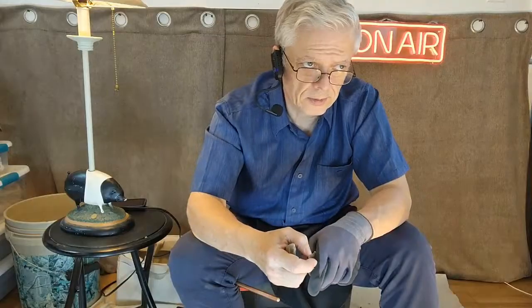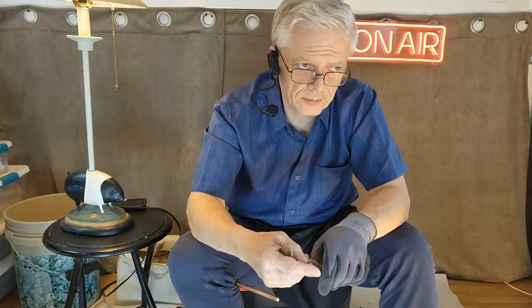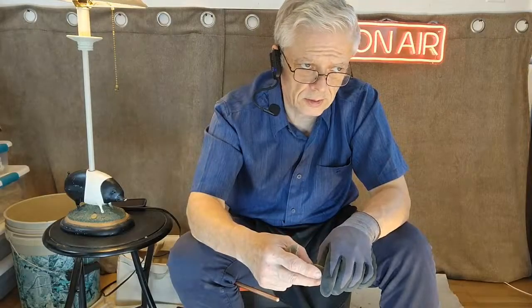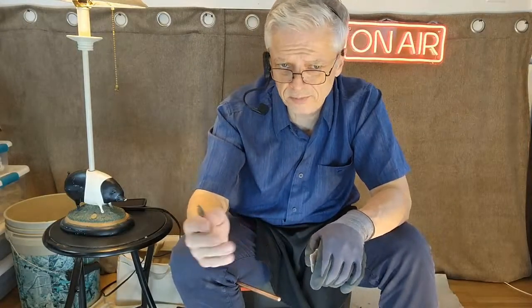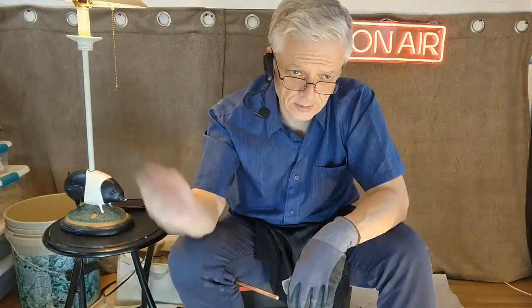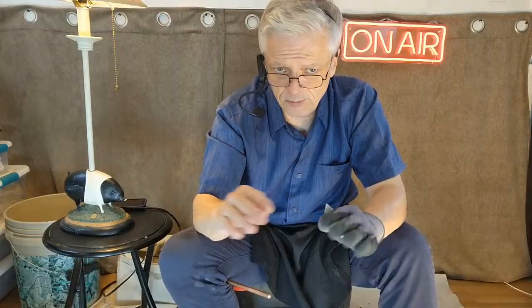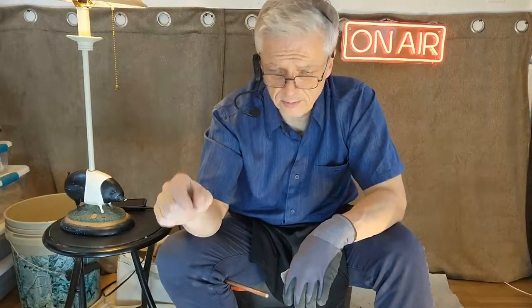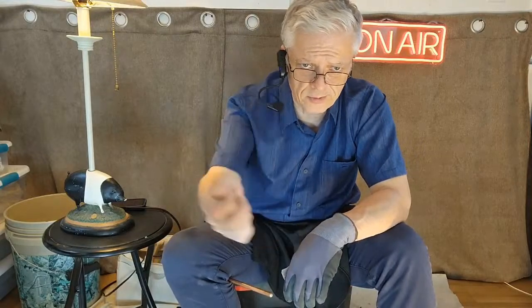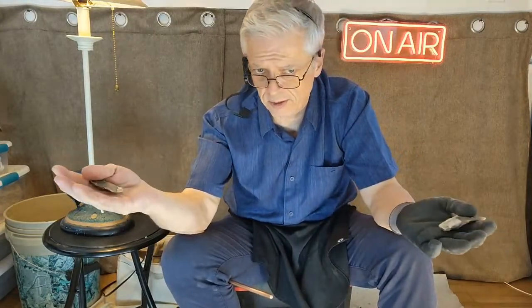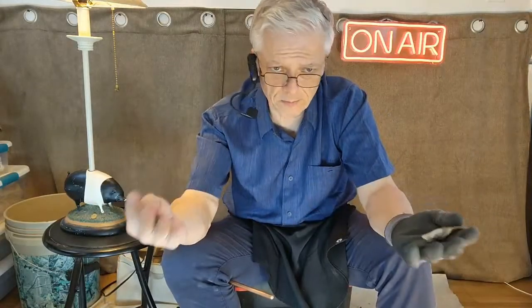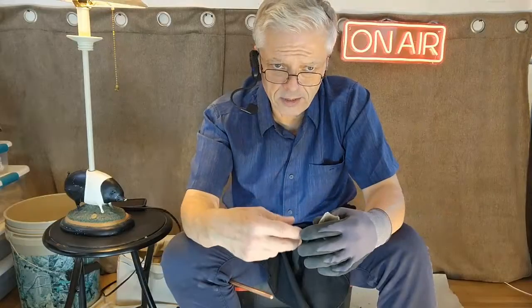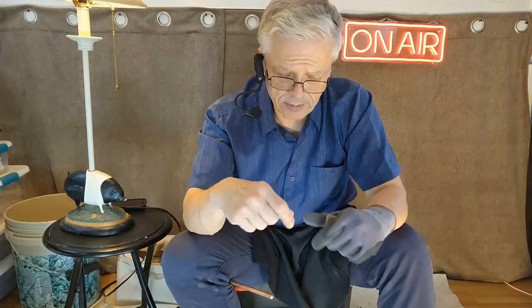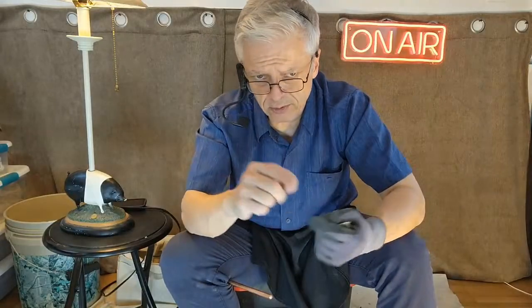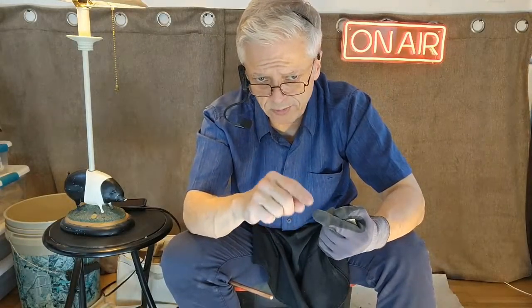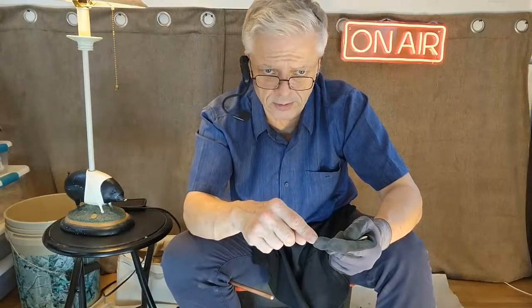Okay, so that particular type of stone that's really tough will probably heat treat at temperatures above 400 degrees Fahrenheit and maybe even require 500 degrees Fahrenheit or more. Let's say you've done everything to get it up to the final test at the maximum on the dial of the roaster, and the temperature gauge says 550. You leave it in there for 4 hours, which is what I recommend, then take it out after 12 hours of cooling, and try knapping it and nothing's changed. Either the stone does not react to heat, or you need hotter than 550 degrees Fahrenheit.